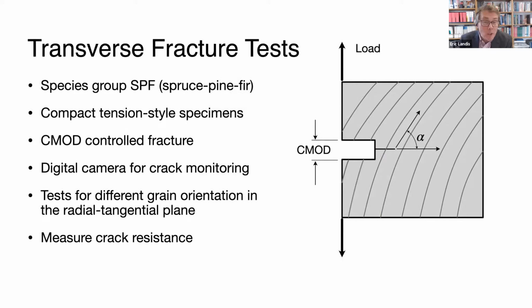For these tests, we use, as is well known in fracture mechanics, a variation of a compact tension specimen. The species we're working with in wood, we always have to be concerned with that. We're actually using commercial lumber for this particular set of experiments in a species group called SPF, which is short for spruce pine fir. These three species are lumped together because they have fairly similar properties. And for this test, what we're trying to do, as best we can, and we realize we're not necessarily going to be successful, is control crack propagation in a stable way. And thus we use a closed loop testing system that uses crack mouth opening displacement as the control mode.